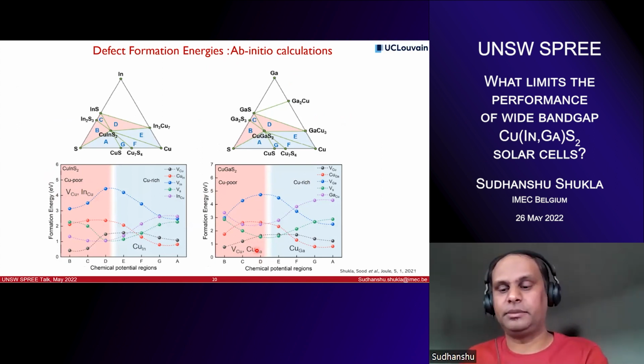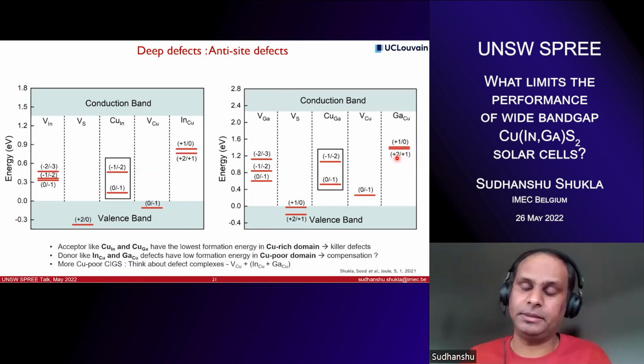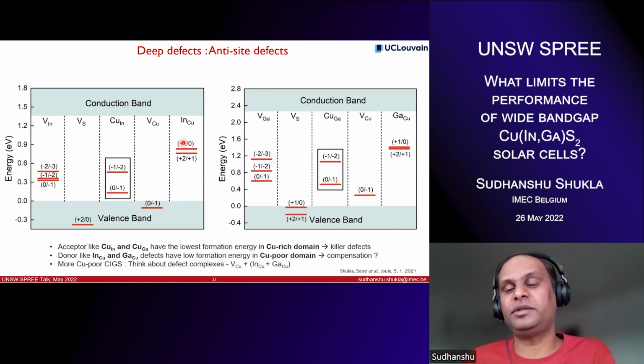I'm sorry, this is gallium over copper. They form these deep defects and their character is more donor-like. So if you are thinking about more copper poor CIGS, you have to also think about the defect complexes, because in one case you have these acceptor type defects, which are copper vacancies, and if they can form a defect complex. So it does not mean that if you make it copper poor, everything is solved. There is another deep defect that is vying for your attention, basically.